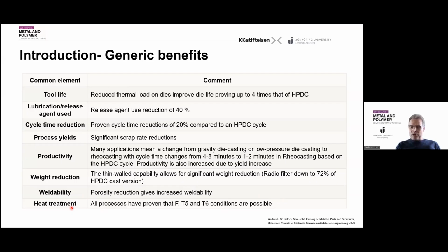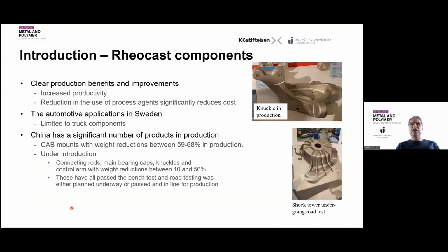So Europe is one of the areas where these processes are growing, but it's foremost growing in Asia and in manufacturing there. So if you look at the Rheocast components that are now out and being used, it's, for instance, knuckles. This is in production and used in cars. We have shock towers. This is a BMW shock tower, which is being road tested at the moment. And both these are produced by a company called Silver Bases in China. And what you can see is that, first of all, you get good productivity. What you get is that you can actually utilize the better ductility to have a weight reduction.